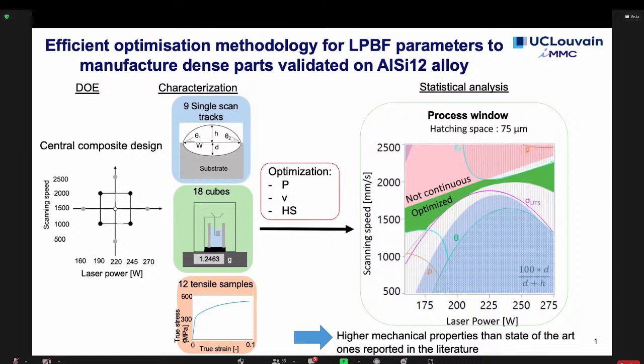Yes, but generally speaking, I think that if we add the manufacturing cost, maybe the optimal region of parameters will be reduced. I think that, for example, too low speeds are not so cheap. Yeah, like you can, for example, say, okay, I want a scanning speed which is more than this. It should also be possible to add the manufacturing cost, but then you also have to increase the laser power. Here we were limited by the laser power of our machine. But yes, it's possible to optimize this also and to add this in the model.